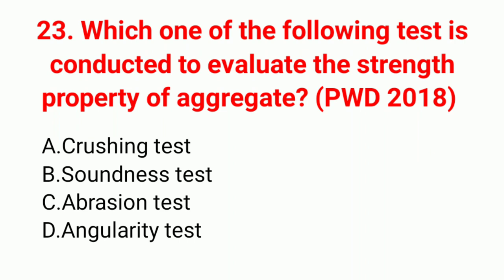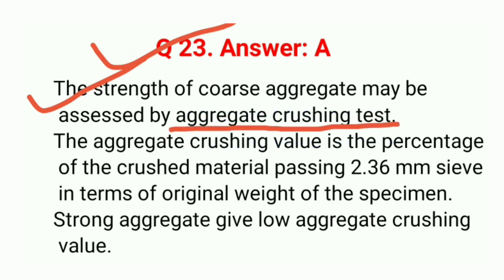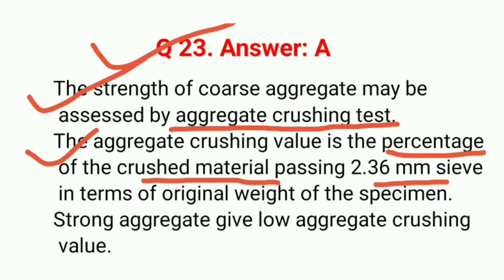Question 23: Which test is conducted to evaluate the strength property of aggregate? Correct answer option A: crushing test. The strength of coarse aggregate may be assessed by the aggregate crushing test. The aggregate crushing value is the percentage of crushed material passing a 2.36 mm sieve in terms of original weight of the specimen.